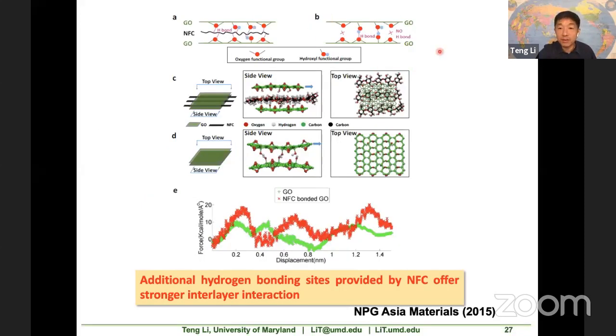Now, if you have just the pure graphene oxide, you make a fiber. On the surface of graphene oxide, they do have functional groups to allow them to form hydrogen bonds, but only a limited number of hydrogen bonds can be formed. However, by introducing the cellulose nanofiber in between, as I showed previously, there are a lot of very rich hydroxyl groups on the surface of cellulose nanofiber. So these significantly increased the bonding sites in the material to form the hydrogen bond. And this additional hydrogen bonding site provided by the NFC offered a stronger interlayer interaction. And we also verified this using molecular dynamics simulation. This shows that the hybrid one is better than the pure graphene oxide one.